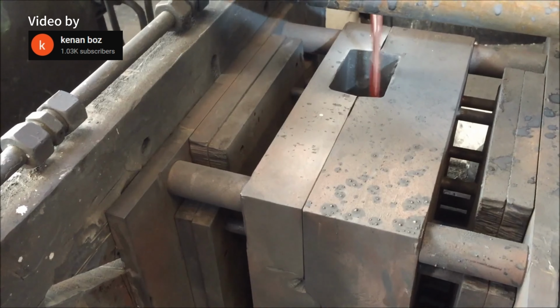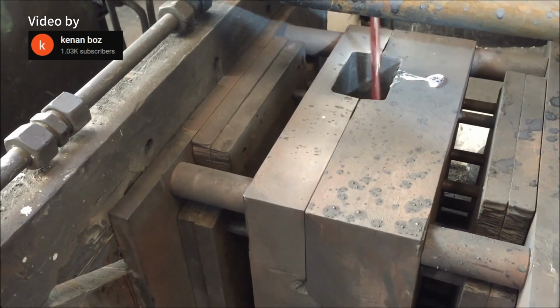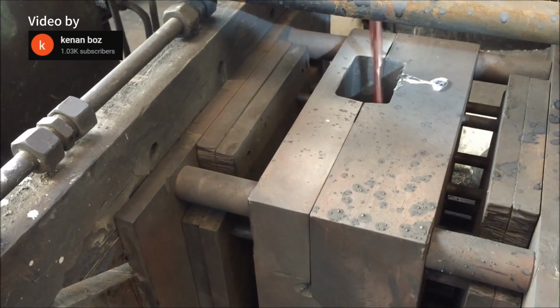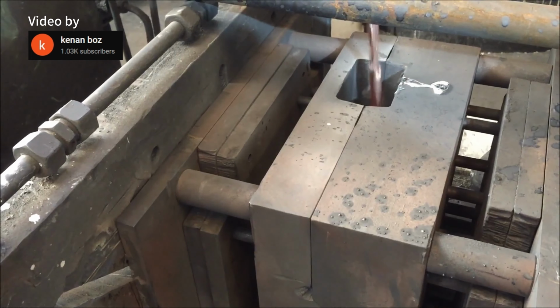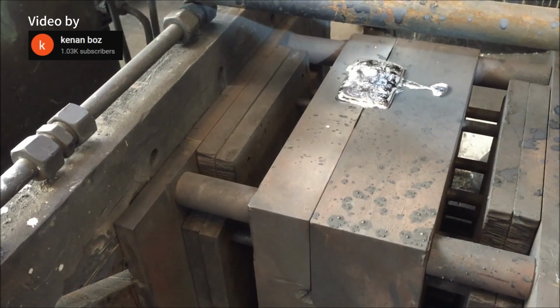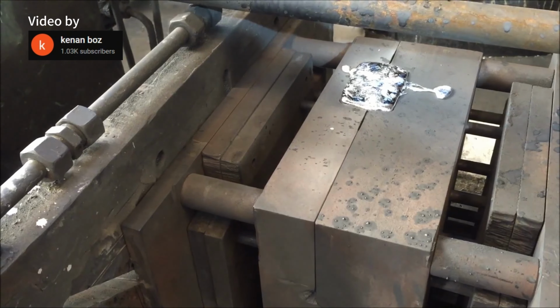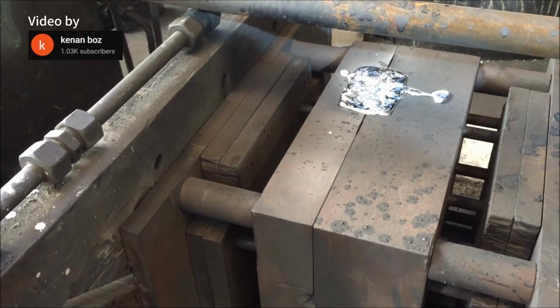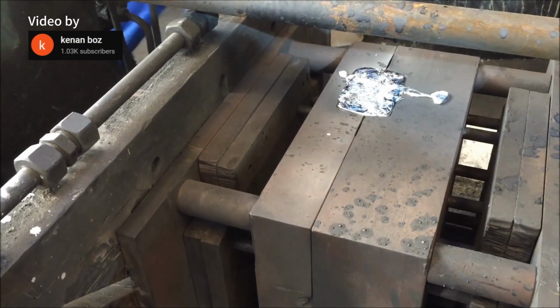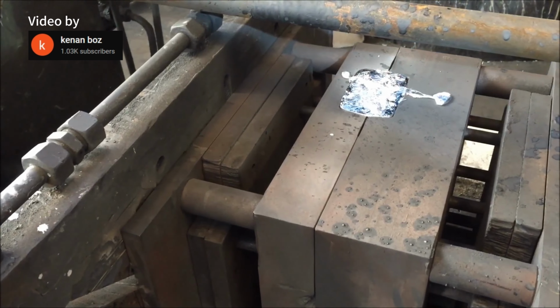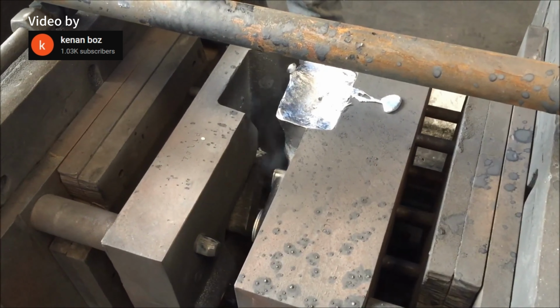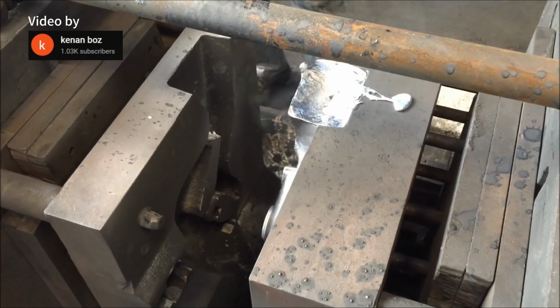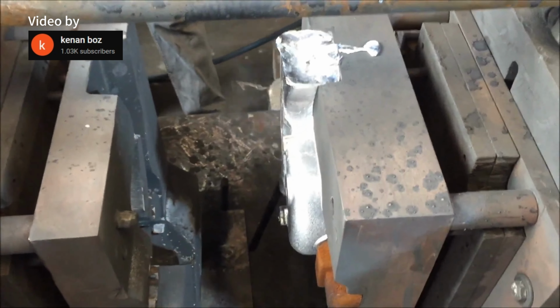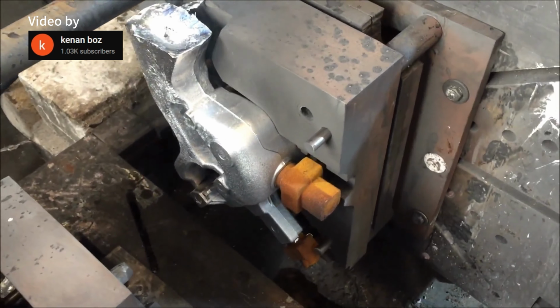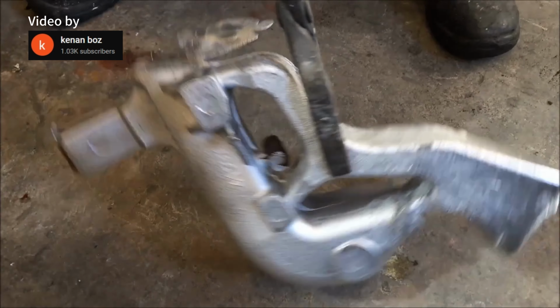Gravity cast parts are strong and have a dense internal structure, making them capable of handling heavy loads. Since the melted aluminum flows more slowly, it traps less air, resulting in fewer pores. This improves durability and reduces the risk of cracking or breaking over time. Because of this, gravity casting is ideal for high-strength and reliable applications, such as automotive suspension systems, hydraulic components, and industrial machinery.